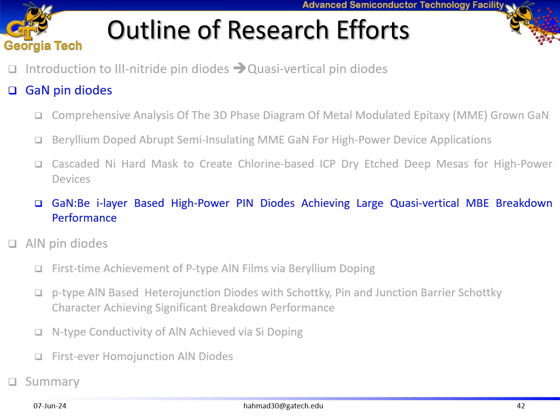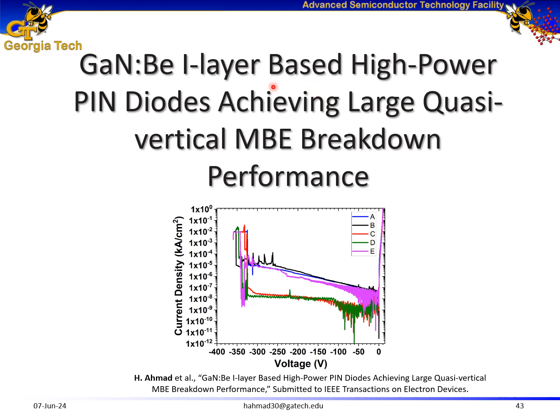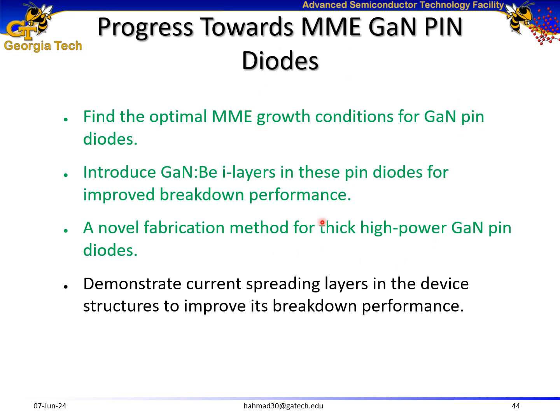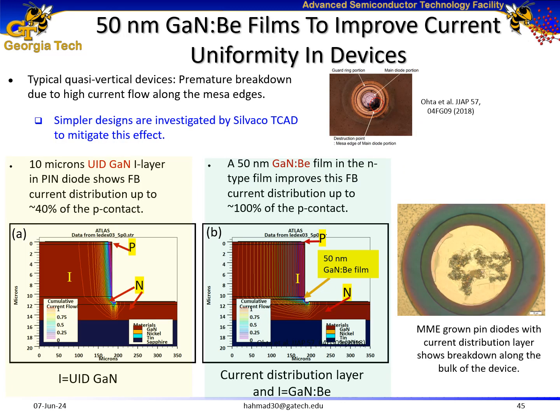So finally, I performed my major study in this regard, which is beryllium-doped gallium nitride I-layer-based high-power pin diodes achieving large quasi-vertical MBE breakdown performance. I've talked about these points where I found the optimal growth conditions, the optimal I layers, and the optimal fabrication conditions for the thicker devices. I still needed to tackle one issue, which is to take care of the high current flow along the mesa edge and to demonstrate a better design. I've shown that due to high current flow along the mesa edge, there would be premature breakdown of the devices. So I investigated simpler designs using Silvaco TCAD and applied them in MBE growth.